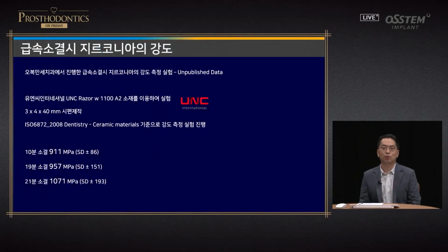There are many questions about rapid sintering. The first question is whether the strength goes down if quick sintering is done. This was something I was curious about as well, so I used a universal testing machine to measure the strength of zirconia. UNC International Razor W 1100 A2 material was used. I followed the ISO regulation to make a specimen, and flexural strength was measured.